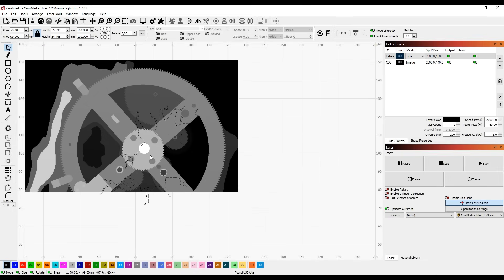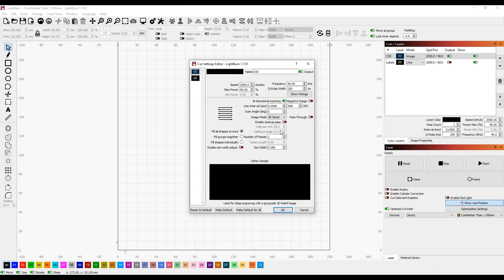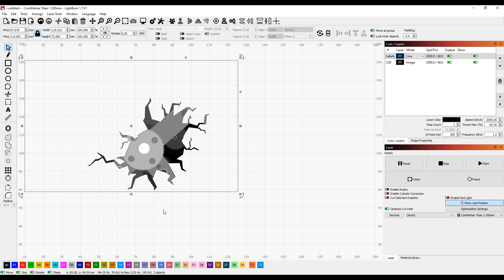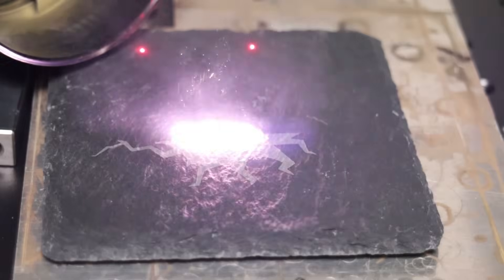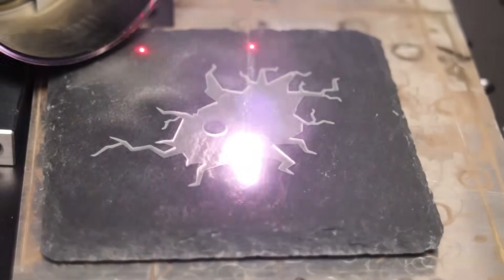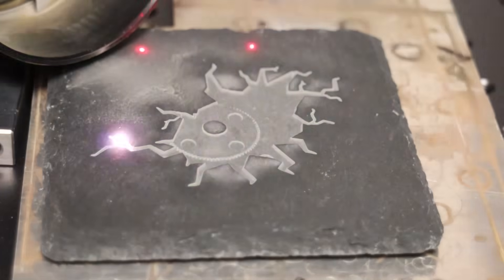Next, I engraved a 3D slice design into stone. One cool thing I like to do is to add a mask to the depth map image, so the result appears like a crack in the stone. You just need to search the internet for images of cracks. The entire engraving, using 64 passes, took just 12 minutes at 90% power with no issues.